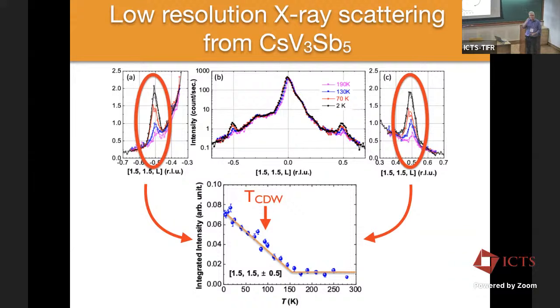And so I was mentioning before that my misspent youth was doing X-ray scattering measurements on measuring critical exponents and such, and for most phase transitions in three-dimensional materials, you can see this sort of critical scattering, but it doesn't go up to twice the ordering temperature. It might go up to 10% above the ordering temperature or something like this. So this is actually very, very large, but it's very characteristic of two-dimensional materials, right? The lower the dimensionality, the more extended the critical range tends to be. Anyway, it's very different than other people's order parameters.